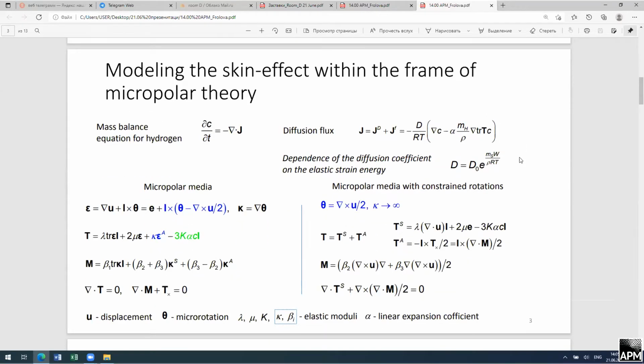Such a phenomenon of skin effect can be described by consideration of material of some samples with different kinds of external loading and by accounting for aging strains due to hydrogenation. The other type of modeling considers some kind of subboundary layer containing different traps for hydrogen, like cracks, microcracks, pores, and other defects. However, all these models assume the existence of such a subboundary layer, but they don't describe how it can appear and don't model it. So they just say that it exists.